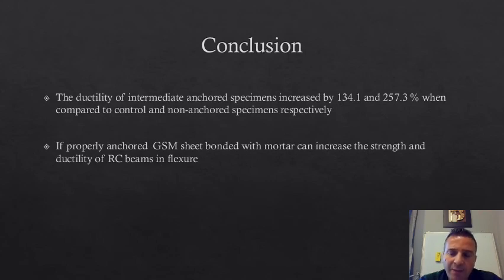Thus, if we anchor a beam strengthened with GSM sheets and a layer of mortar, then basically we are not going to worry about the delamination or the debonding failure modes, and the beam will fail in a ductile mode, which is favorable. According to the literature, there is a lack of experiments that anchored beams with GSM laminates at the ends and intermediate locations. So this will add some data to the open literature. We are right now doing something with epoxy, and we are going to combine both of them, and maybe we can write a very good journal paper that will be submitted to one of those well-reputed journals.